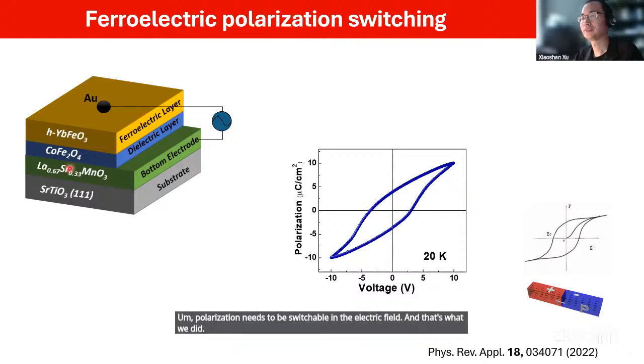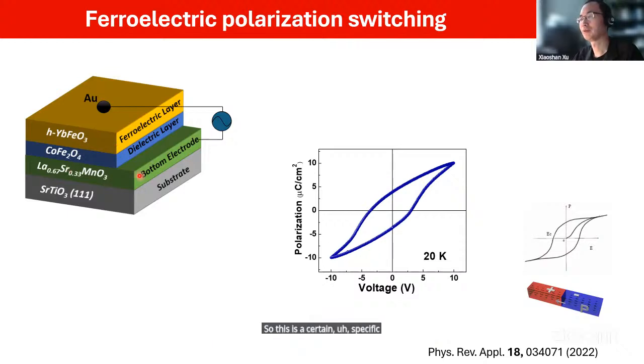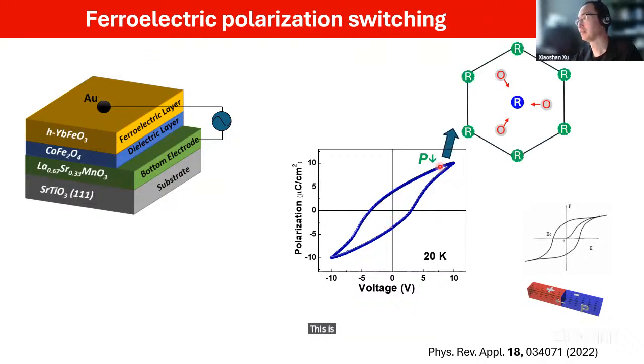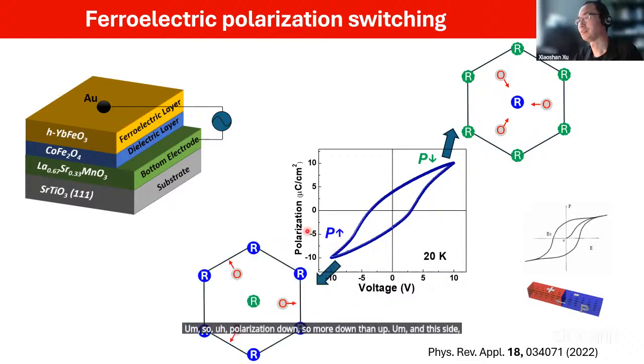So this is a specific material that we made for this data. Okay, and you can imagine if you apply enough voltage to this point, this is the state you get in. So polarization down, so more down than up. And this side, it's opposite, right? If you apply a low enough voltage, you can switch the polarization to this state. Okay.